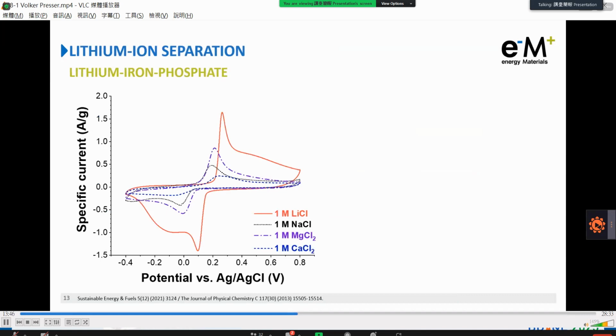Indeed, lithium iron phosphate is not just a very exciting battery material on the verge of replacing, for many electric cars, the established nickel and cobalt containing cathodes, but it's also a very interesting material from an electrochemical point of view. When exposed to single salt systems, we see a very large current response when immersed in lithium chloride compared to sodium, magnesium, and calcium chloride. But single salt systems don't tell you much about selectivity.